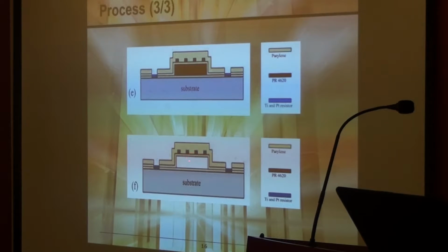And the reason why it can go up and down is because this design is actually very similar to our previous case. With the previous case, though, it's longer and shorter, thinner and wider, right? So here, we try to make something different. Above this heater, the lower layer is thinner. The upper layer is thicker. So when we do the heating, the top layer feels very little heating. And the lower layer feels more heating, large deformation. So finally, you will find a large deformation versus a small deformation.